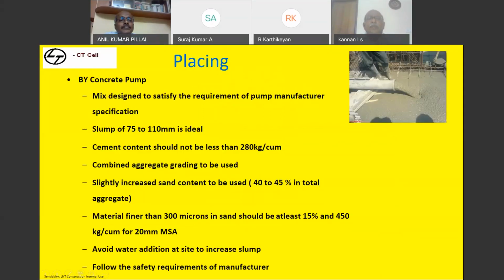When the concrete is placed by pump, the mix should be designed to satisfy the requirement of the pump manufacturer's specification. Normal slump of 75 to 110 millimeter is ideal. Cement content or cementitious content should not be less than 280 kg per cubic meter. That is a minimum mandate for a smooth pumping. People can say, I can pump a PCC even with 220. You can pump, but many times the pumping will get choked. If you have a cementitious content of around 280 with sufficient sand content, the pumping may become easier.